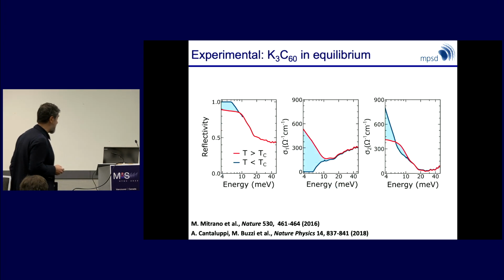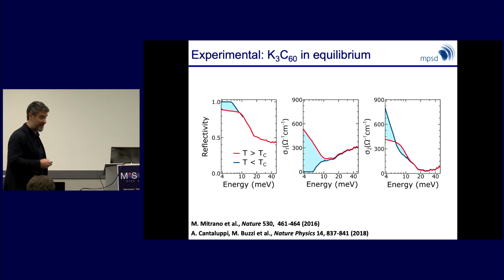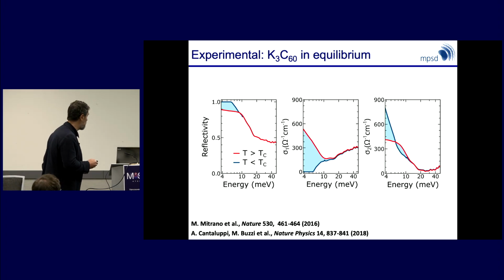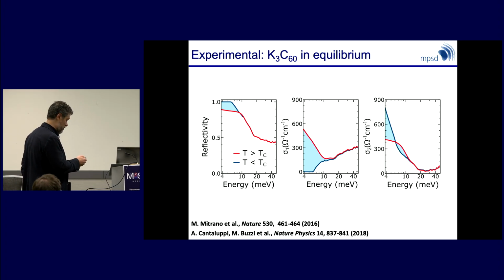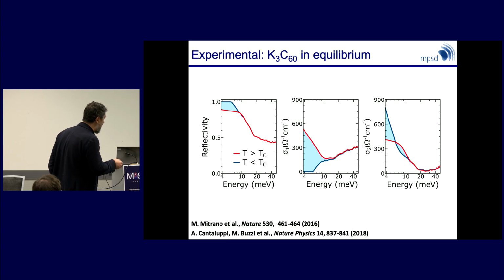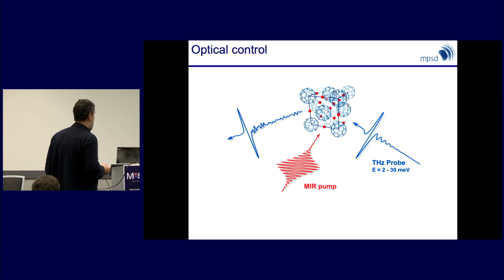These are optical measurements that were done at Elettra by Matteo Mitrano when he was a PhD student with me. And you can see in equilibrium, when you cool down these powders that we have, you observe the formation of a gap at about 2 terahertz, an imaginary part of the conductivity that diverges because of this delta function at low frequencies, and a reflection coefficient of exactly 1.